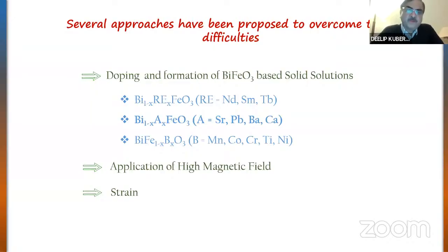The first approach, which is very popular, and we are material scientists. So basically, I always say that we are basically solid state chemists. Actually, we have to become solid state chemists, because we never thought about chemistry as important. Now we feel that when we work in mixed oxides and new material development, chemistry plays a very important role. So the first approach is doping and formation of BiFeO3 based solid solutions. You substitute either rare earths on the bismuth side, or alkaline earths such as strontium, lead, barium, calcium on the bismuth side, or directly at the Fe side you substitute some 3d transition metals: manganese, cobalt, chromium, titanium, nickel. This is called chemical doping. This also helps in overcoming some of the difficulties faced in the use of BiFeO3.